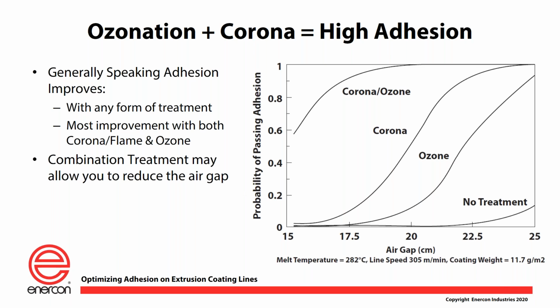Which also leads me to a point that I get asked from time to time. People say, well, can't I just ozone treat it? Can't I just take a substrate and pass it through an ozone treater and then put it in the extruder process and see if that doesn't work? Well, that doesn't work. The ozone treaters are really only used for the specifics as we've discussed here, that being they're used in a manner to put ozone onto a molten extrudate. They don't really work relative to treating a pre-made film.